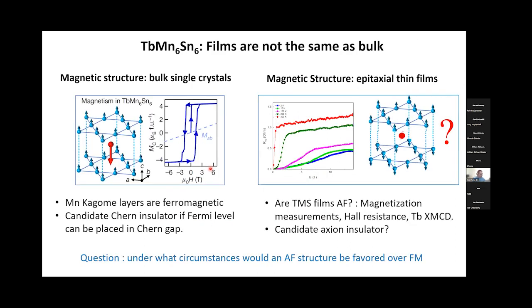In one word, to summarize everything: in the bulk single crystal, the magnetic structure of the moment in the kagome layers is ferromagnetic order. But in the film, we are still not sure what really happens for the magnetic structure. So one question is under what conditions the antiferromagnetic structure could be favored over the ferromagnetic order.